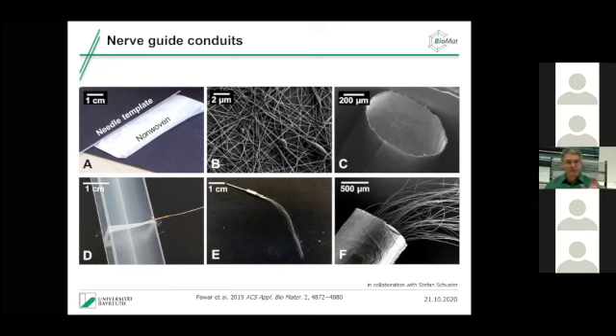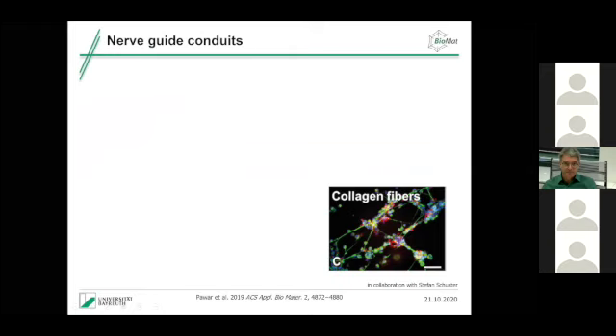Second setup that we used, I've shown you before the self-rolling films. We can also use silk nonwovens per se and roll that up and then bring in the collagen fibers. So this setup is more similar to the setup of the Hannover group, but instead of having a cover vein, we have a silk nonwoven, and we have collagen fibers instead of the silk fibers. And this setup also works quite well.